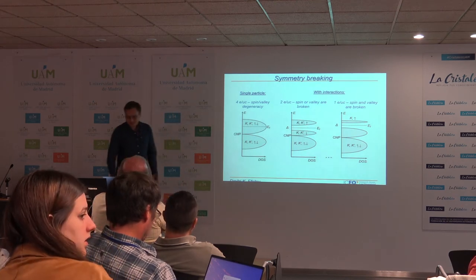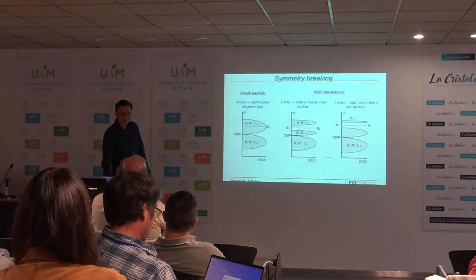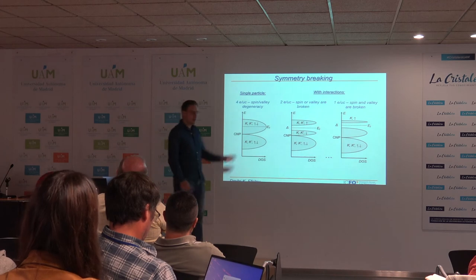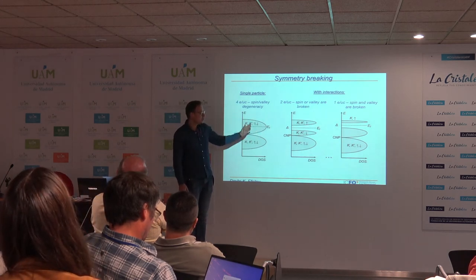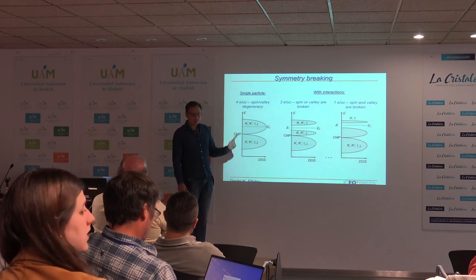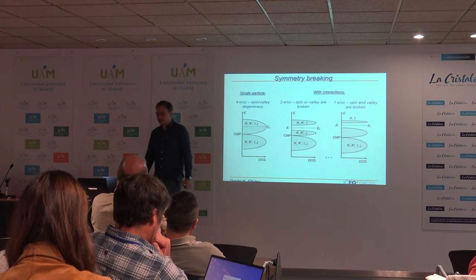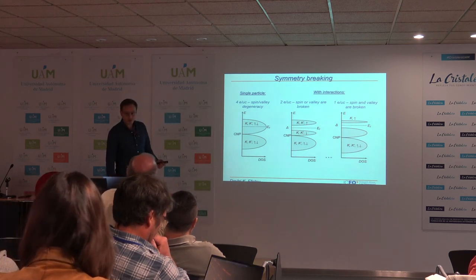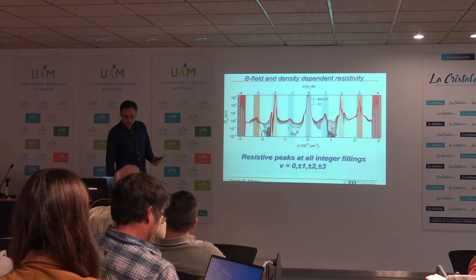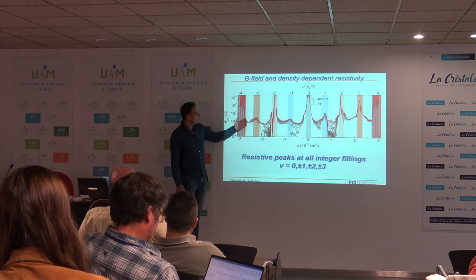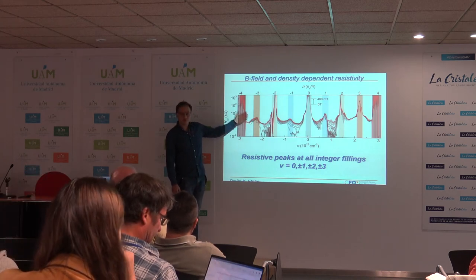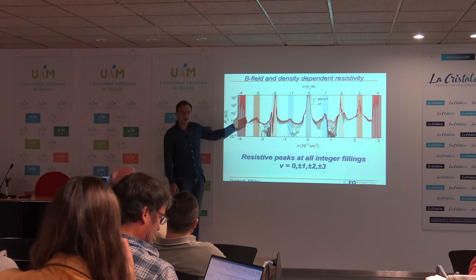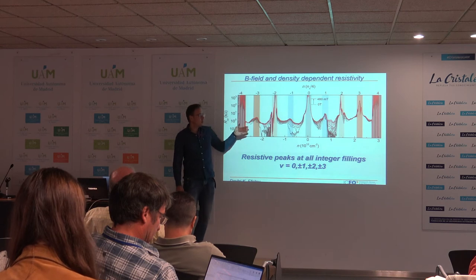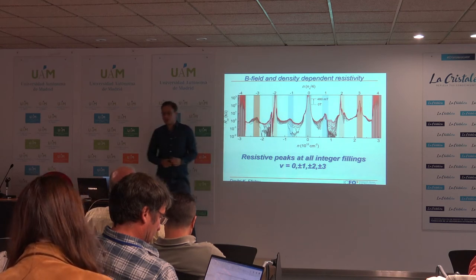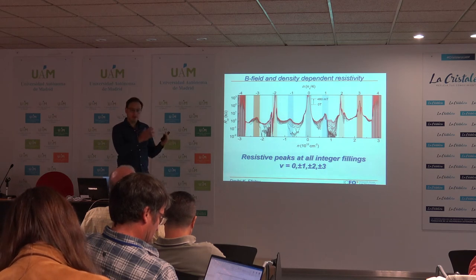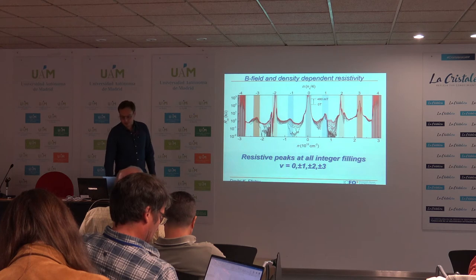consistent. Again, these pictures are not to tell you the final story about this valence technique. This is just really to explain the possibilities we have to take into account. So really the message here is that we have 4 degrees of freedom: K, K prime, spin up, spin down, and in principle all of these degrees of freedom might be broken. I think the way I'm thinking about our results now, that at every integer filling we observe a correlated insulating state, means that we probably split the whole Moire band into regions where basically the band splits up into all of these degrees of freedom. That's a very likely scenario, I think.